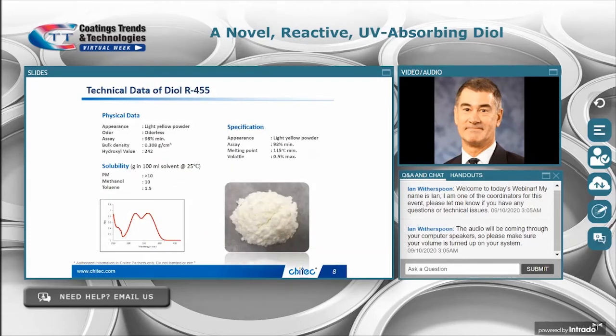Okay, the material is usually a very light color, like a benzotriazole always is. It doesn't bring in enough color to impact a coating at the usual coating thicknesses. So if you go 25 to 50 microns, things like that, you can't really see the yellow color. Its solubility allows for a very practical synthesis and formulation, and it's delivered at a very high degree of purity. Our assay is listed at 98% or better. So that's pretty good.